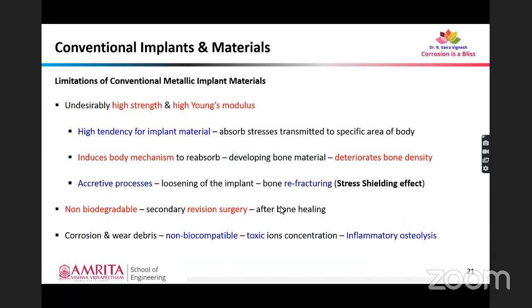Why it is not desirable is that this undesirably high strength and Young's modulus creates a tendency for the implant material to absorb the stresses that are normally transmitted to the specific area of the body. That will result in resorption of the developing bone material, and that will deteriorate the bone density. So the tendency of the implant material to absorb the stresses and the deterioration of bone density will lead to loosening of the implant and will ultimately result in bone refracturing. This process is generally called the stress shielding effect, and it is prevalent in conventional metallic materials.